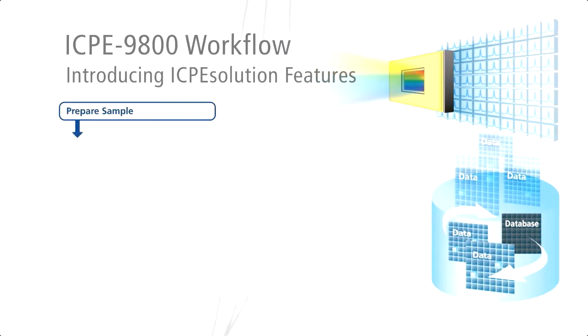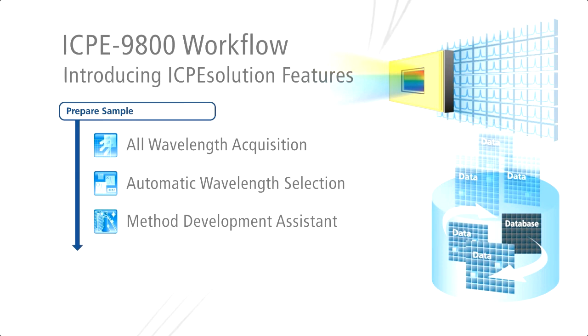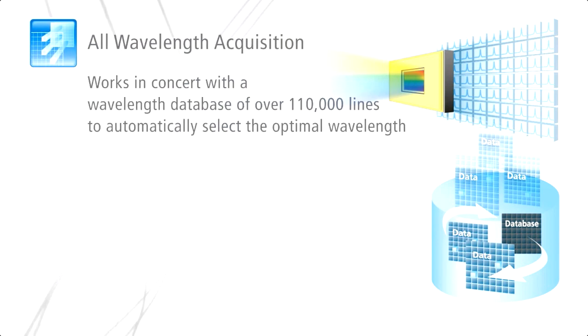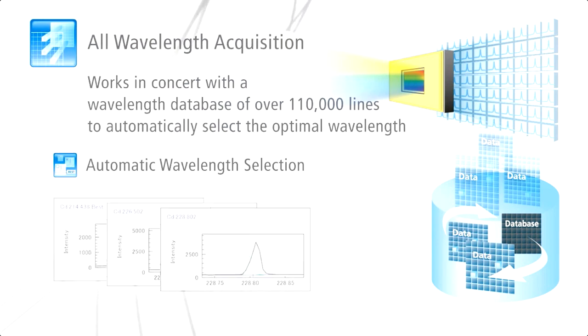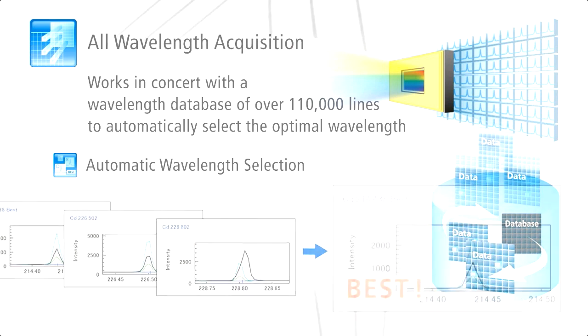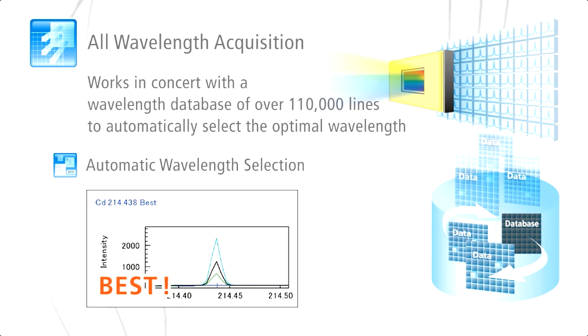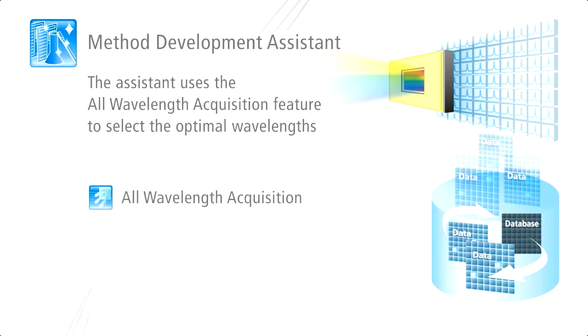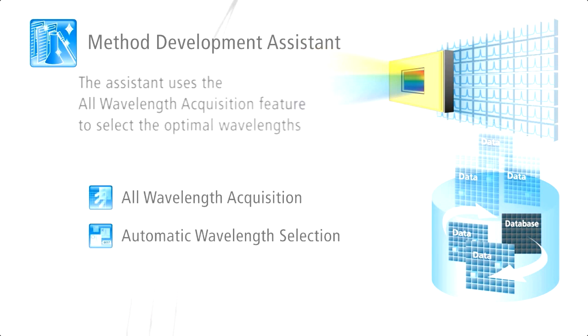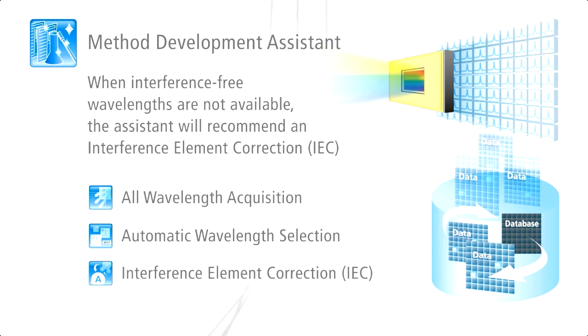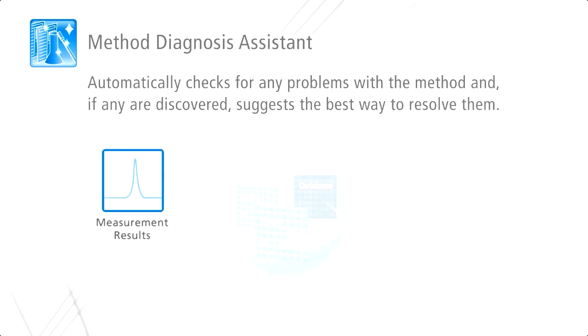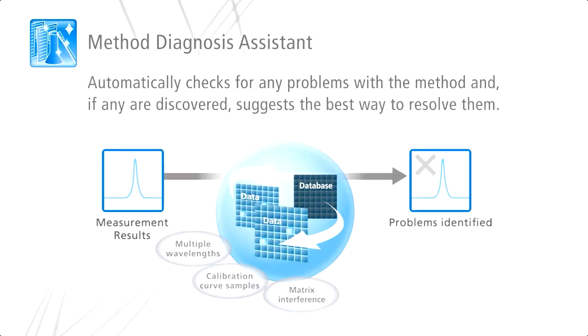The Shimadzu ICPE-9820 allows for a full range wavelength acquisition that can be very useful for this complex sample. With the full range wavelength data, you can easily identify and qualitatively measure all impurities present in the sample. Additionally, if a multi-element calibration standard was used during the method setup, elements that were physically in the calibration standards but not selected for analysis in the method can be reprocessed and quantified after the samples are run by creating a new calibration curve using the existing data file.